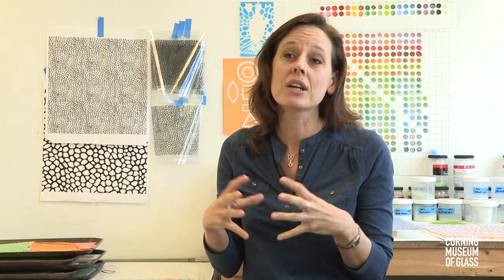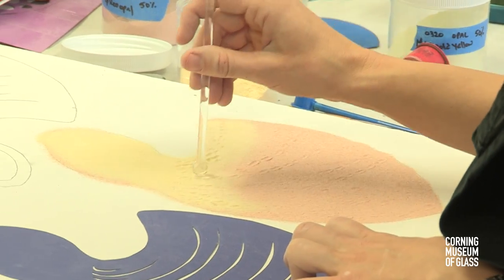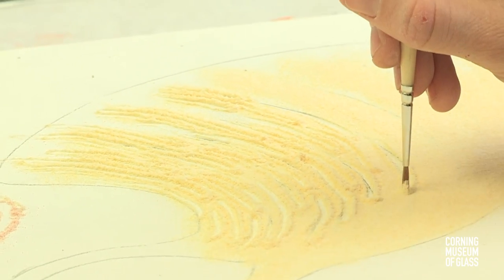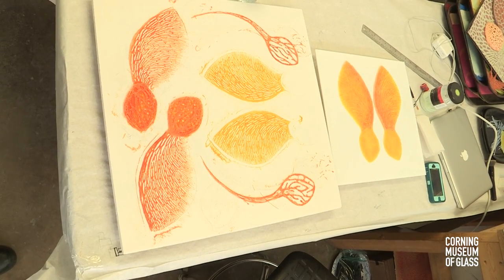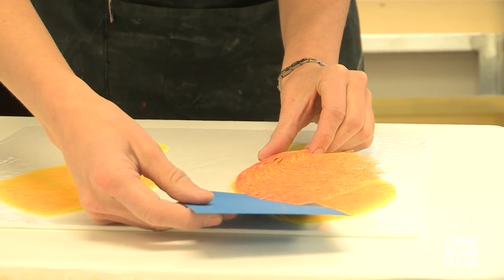One of the biggest challenges I had in the early stages was just the shrinkage of the material. As the powder heats, it squeezes in on itself. So if you're adding five or six different layers, those aren't necessarily going to match up by the time you get them fired, because as the glass squeezes, it shrinks and bends. So I really wanted to do some time trials, some shape trials, and work through some of those to get more predictable effects. I've been able to work through some of that and learned different ways through sheer trial and error.